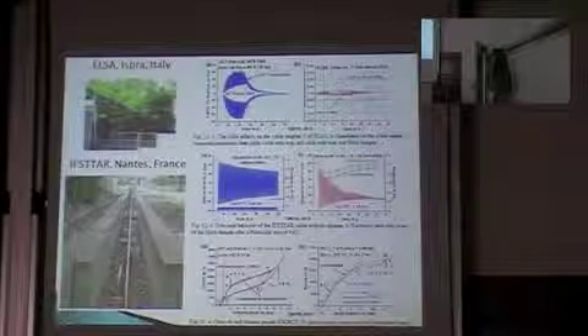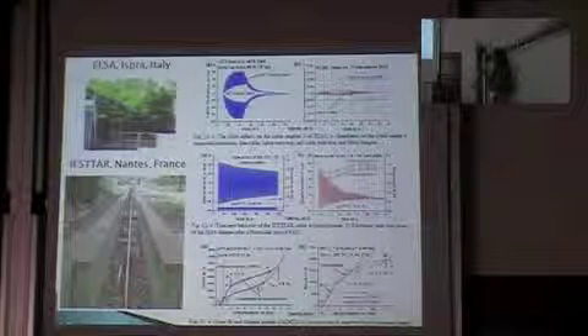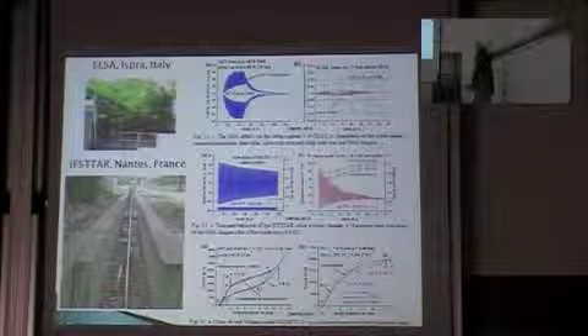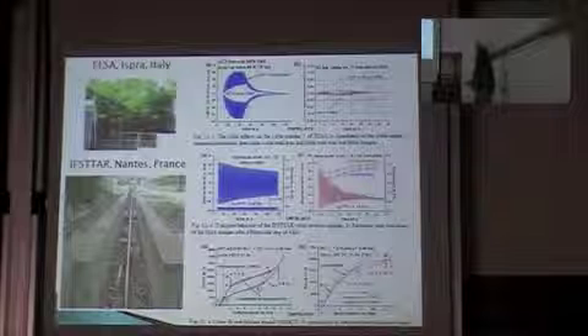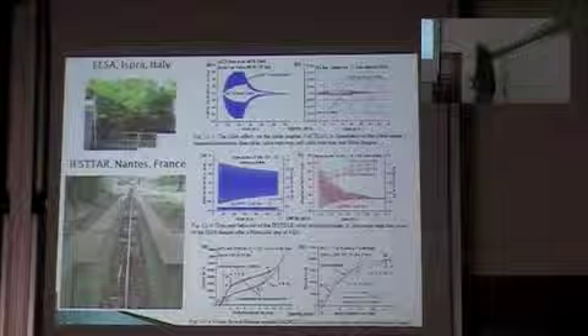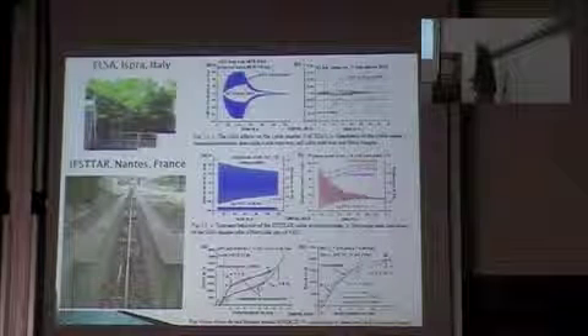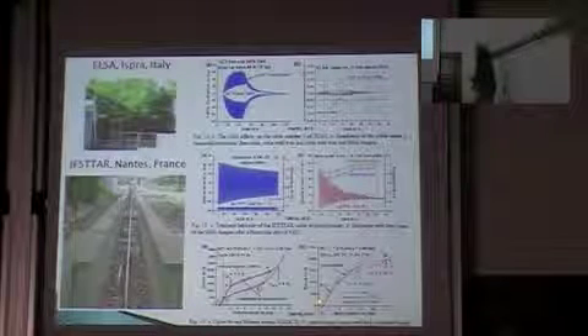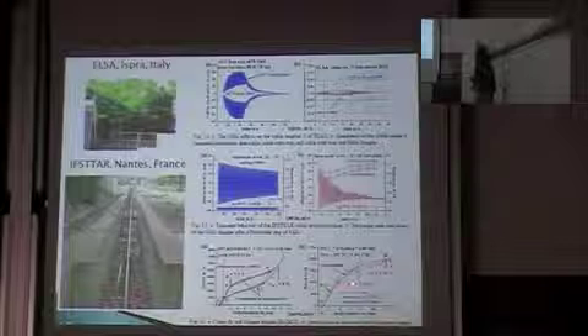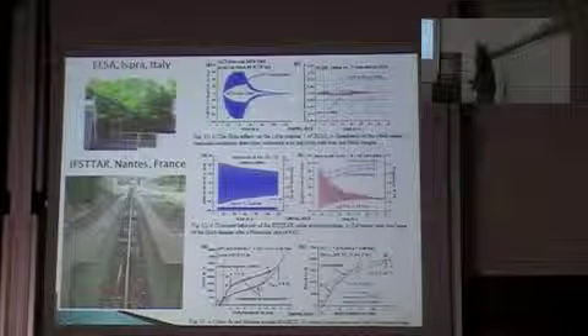The bilinear model gives very good results for earthquake engineering. And that's the one that typically we adopt when we have the uniaxial case of shape memory alloy that is a wire. But when we use lower level of deformation, to obtain a good agreement with the experimental results, it's better to go with a cubic fit. And in this case, we can actually obtain the realistic energy dissipation capacity of the device. Instead, if we rely on the bilinear model, we overestimate our damping capacity.